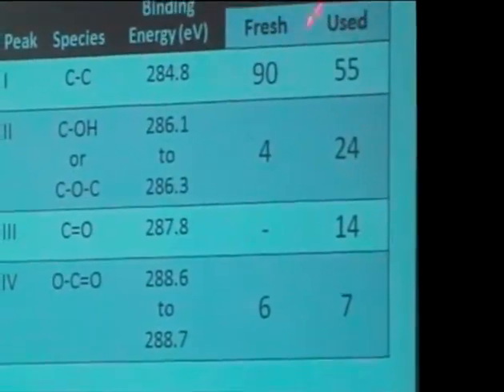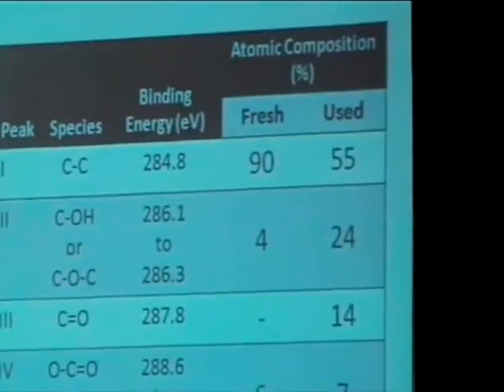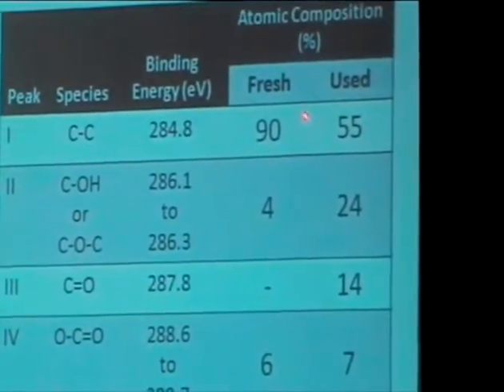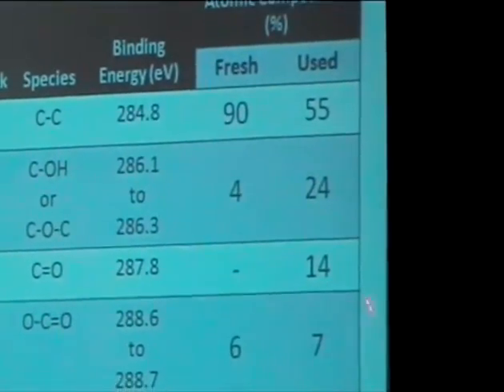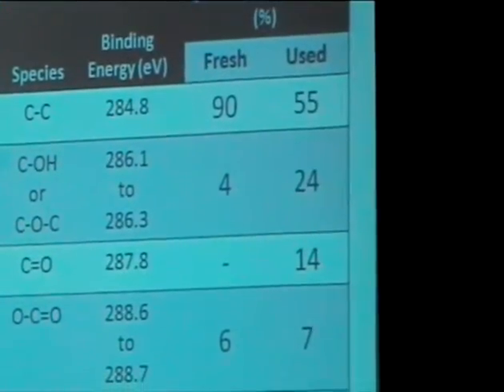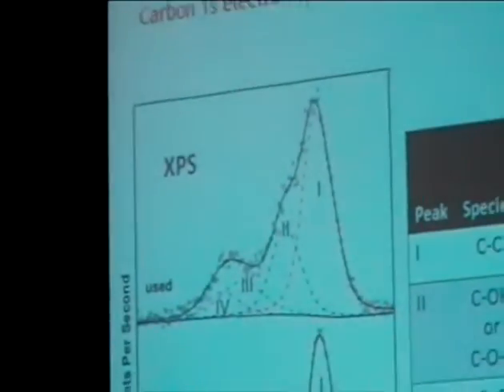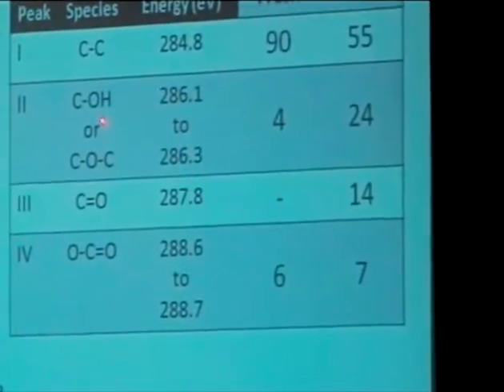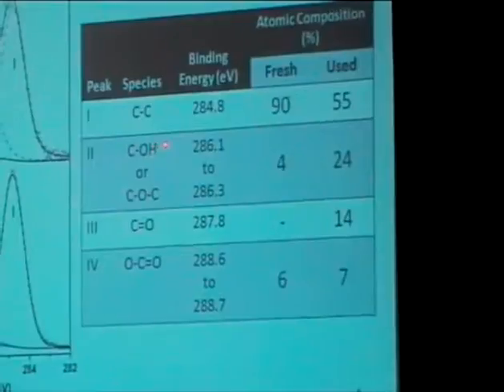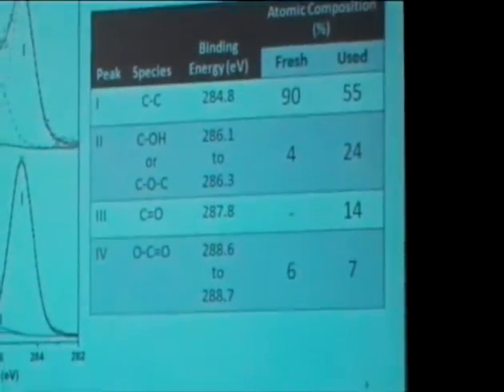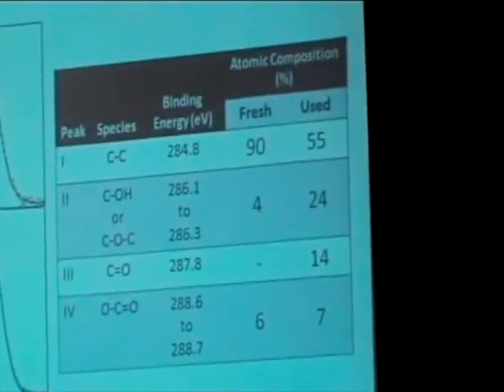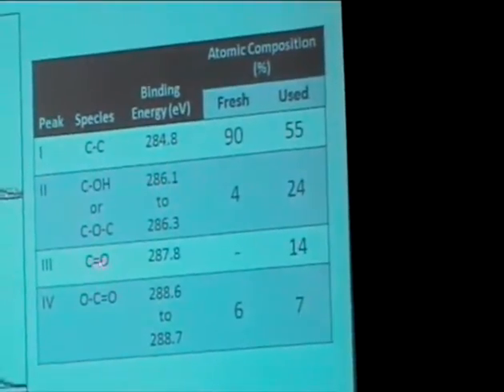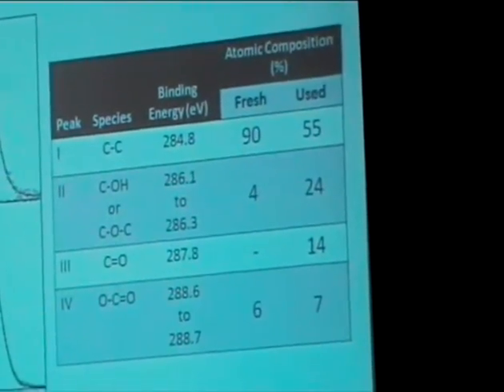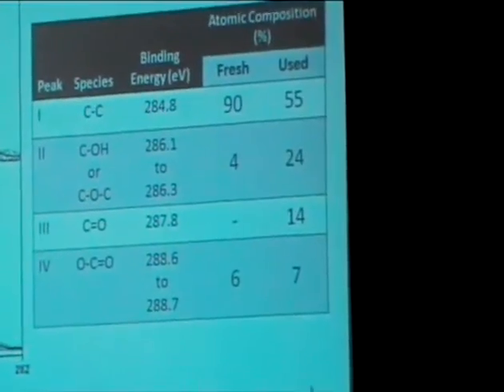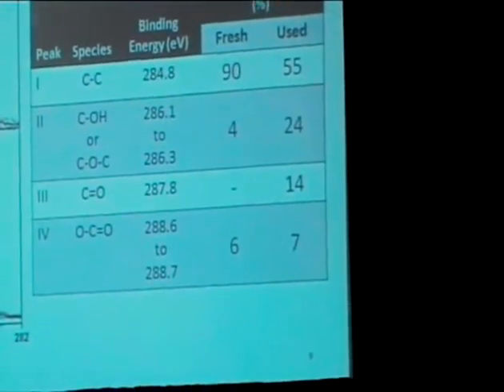After the catalyst has been used for a day or so on stream, we do the same experiment here, and what we find is a whole series of oxygenated materials that are adsorbed on the catalyst and cannot be easily removed from the surface of the catalyst. These are both alcohol, ether materials, which make up the bulk of this material, but we also see various types of carbonyl and acidic components also appearing on the surface of the same catalyst.